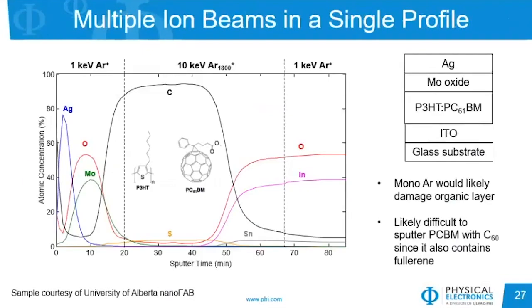So the first example that I will show is a stack of inorganic layers with an organic layer in between and then inorganic layers below. So we have silver, a molybdenum oxide, and then a polymer layer on top of ITO and glass. In this case, what we are able to do is start with monoatomic argon for the inorganic section of the profile, and then once we start getting into the organic layer, we can either stop the profile and switch to an argon gas cluster, or we can program that directly into our profile ahead of time to change guns and use the argon gas cluster. And therefore we can maintain the chemistry of the organic layer, and then once we reach the inorganic layers below, we can switch back to the monoatomic gun for better performance.